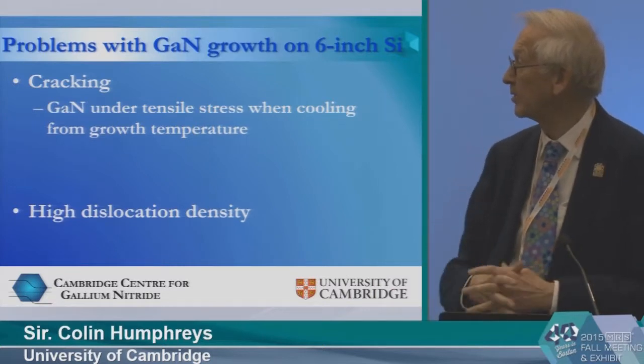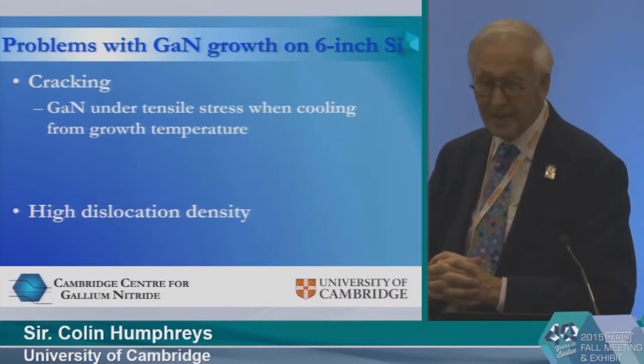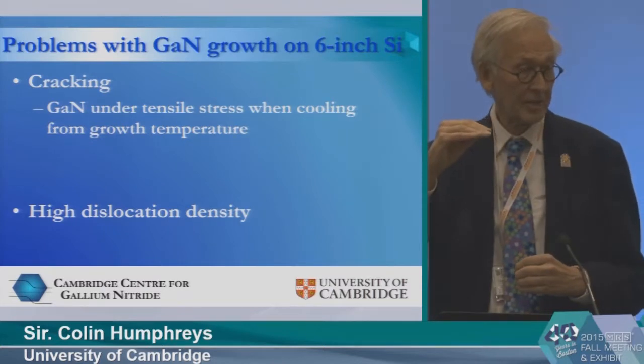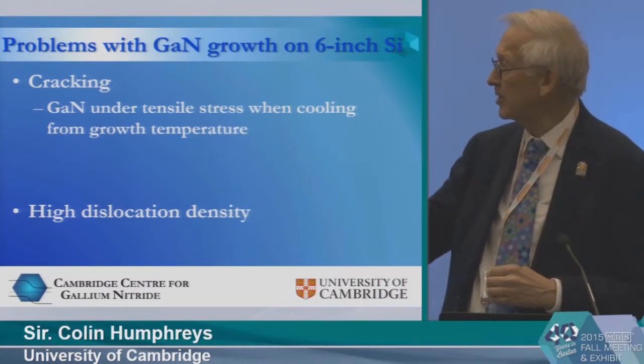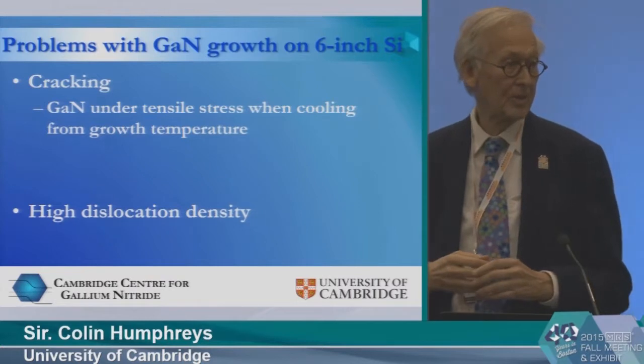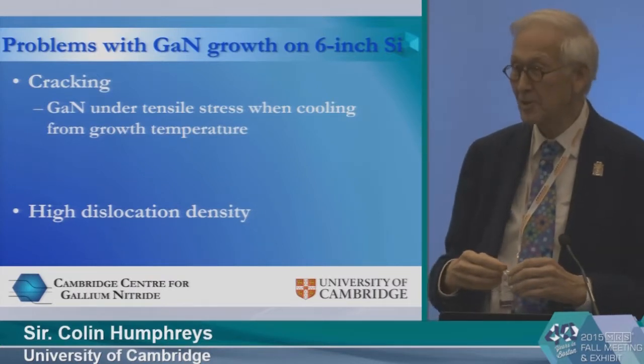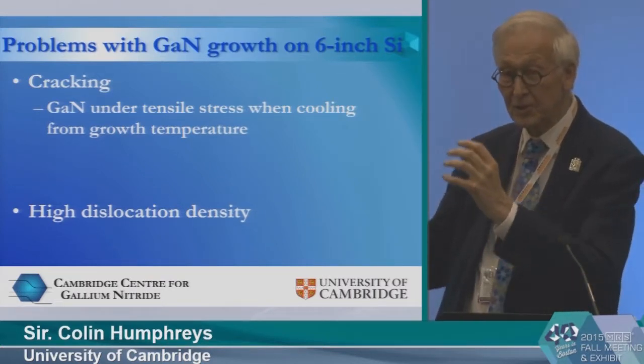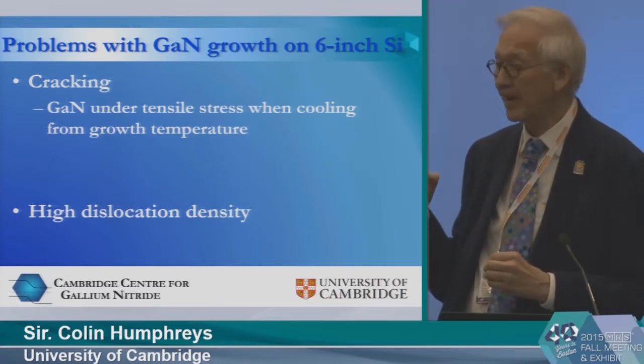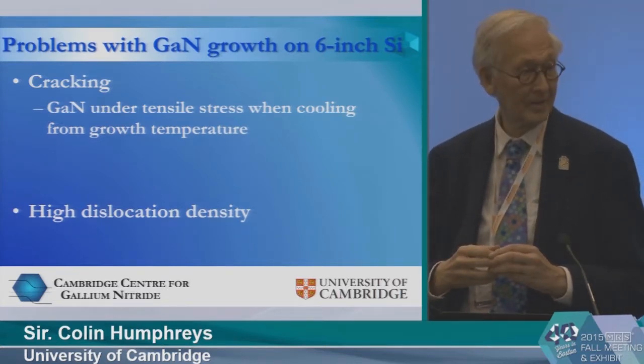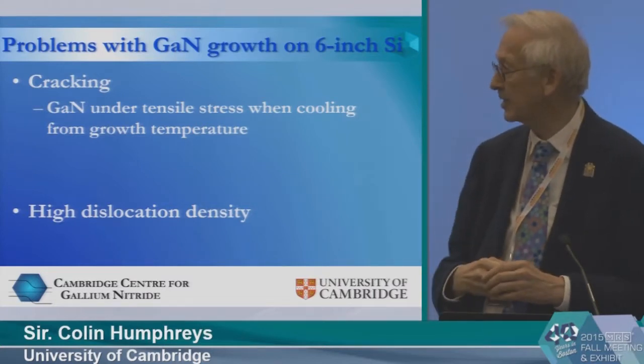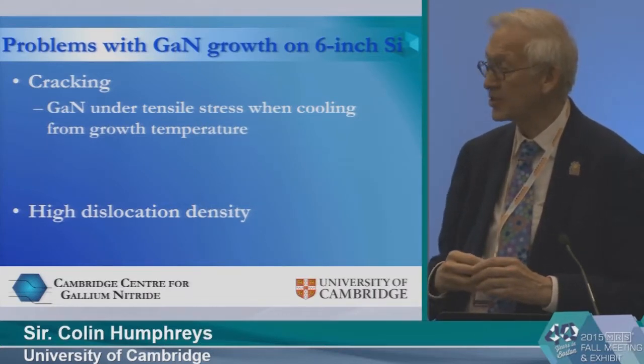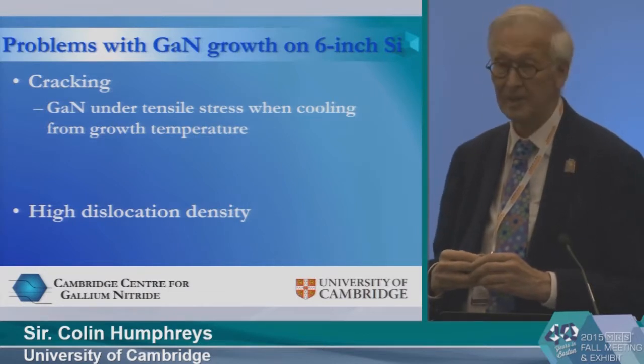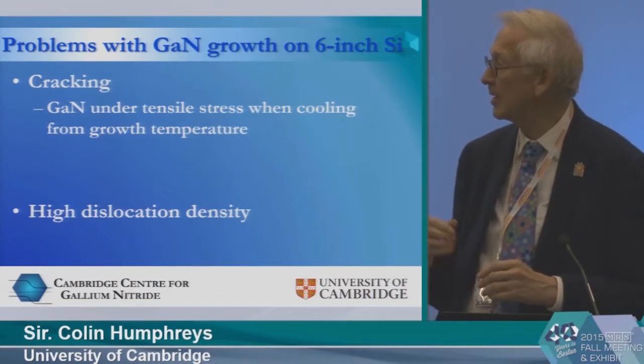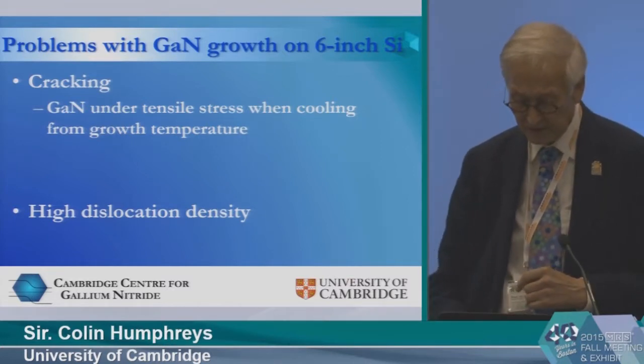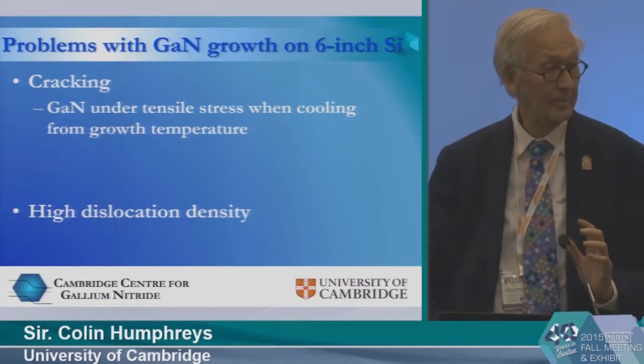So, problems with the GaN growth on 6-inch silicon. The first one is cracking, because you grow at 1,000 degrees centigrade. When you grow the gallium nitride on the silicon, the thermal expansion coefficient mismatch is 52%, which is huge. The gallium nitride is in tension when you cool down and it cracks. So you have to put in compressive stress deliberately when you grow, to counter this tensile stress and cracking. The other factor is the dislocation density is very high when you grow on silicon, about 10 to the 10 per square centimeter, and we have to do dislocation reduction techniques. And those are both quite difficult, but they can be done.